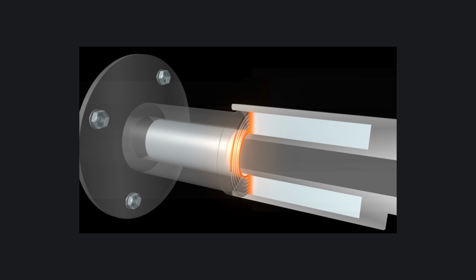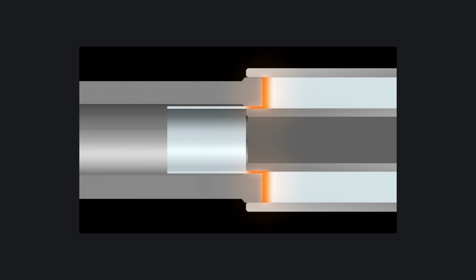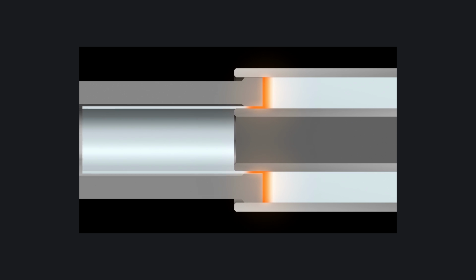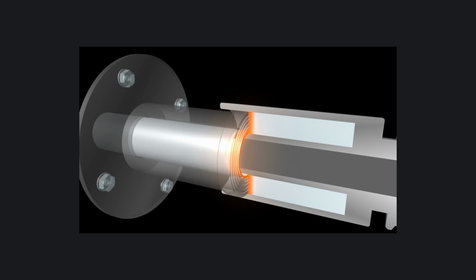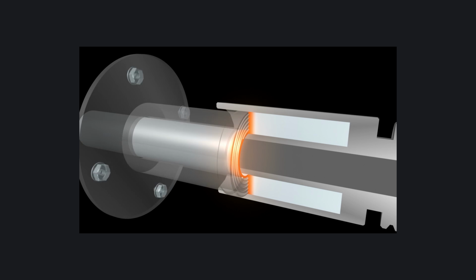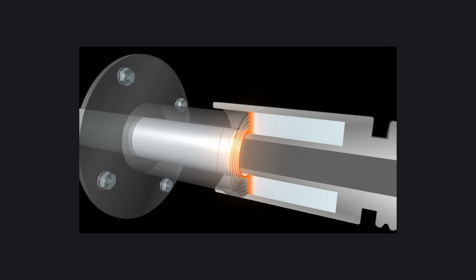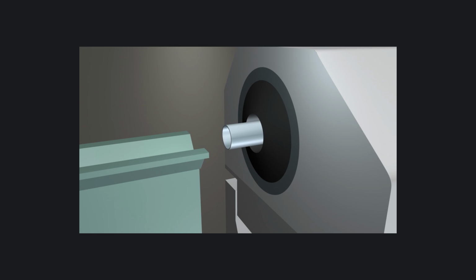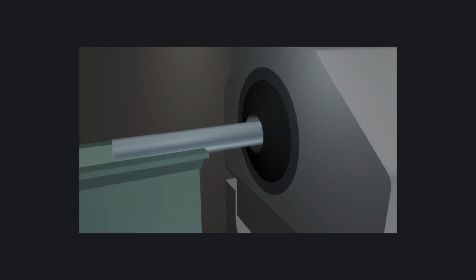Spinning also orients the grains to improve the energy absorption of magnesium, so it's equal to aluminum and can be used for more structural components. The process is cheaper too, with far less electricity needed. It's shaping up to be an important advancement for the auto industry, which hopes to use an average of 350 pounds of magnesium per vehicle by 2020.